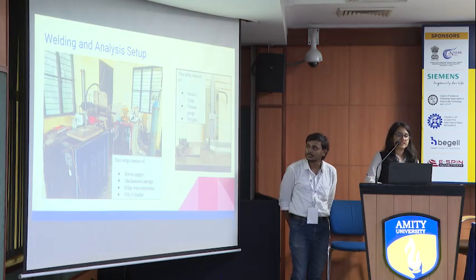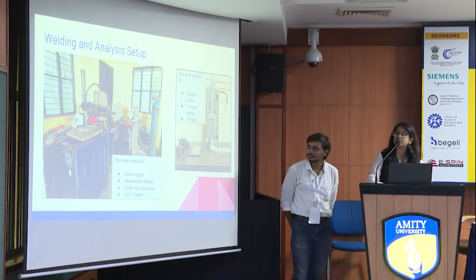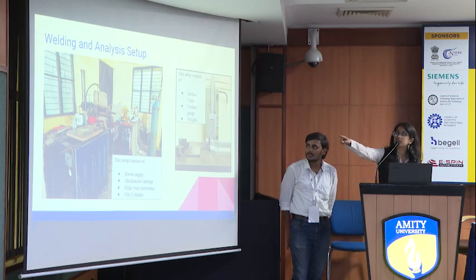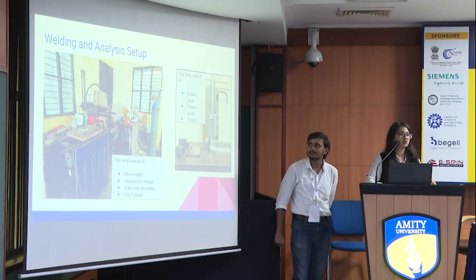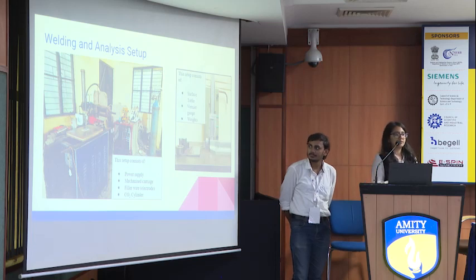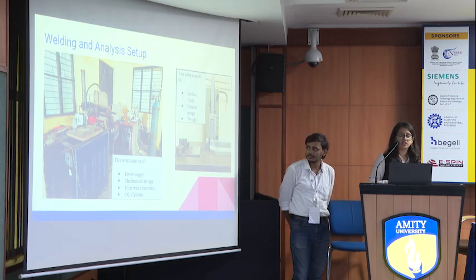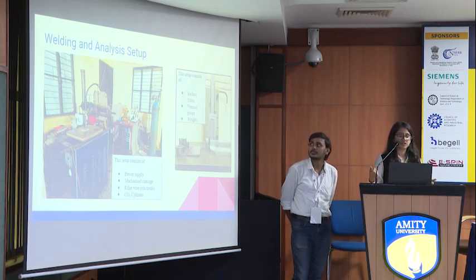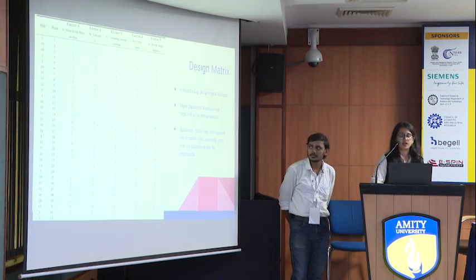This was the welding setup that we used. Here we can see the power supply. The carriage was mechanized. We used the filler wire spool, as you can see over there, and a CO2 gas cylinder that we have used as shielding gas. After we have welded the plates and obtained the new welded plates, we measured the angular distortion using a vernier gauge, surface table, and weights. Now I would like to call Aryan to go ahead.